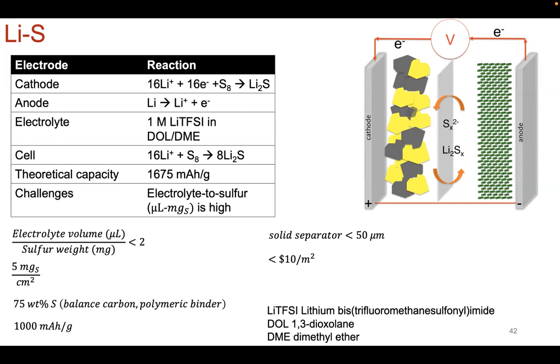So the challenge here is the solubility of sulfur in the lithium polysulfides in these electrolytes. So what we'll be focusing on is how to achieve parity with, let's say, lithium metal batteries with NCA cathodes, or lithium ion batteries with graphite even. So we'll focus on the electrolyte to sulfur ratio, because right now that ratio is quite high.